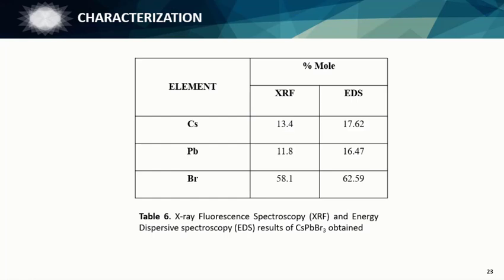Since the X-ray fluorescence technique is a more superficial technique, although the values are slightly lower than the energy dispersive spectroscopy measurements, it is understood that the ratios of cesium and lead in a single crystal are very close to 1. The excess of cesium is ideal because of the 1.45 cesium to lead ratio in the precursor.